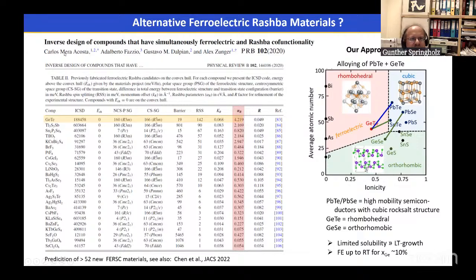Actually, there have been some recent publications by Alex Zunger's group, on inverse design of compounds with ferroelectric and Rashba functionality. And in this paper, they published a table with more than 52 compounds that they predict to be ferroelectric Rashba semiconductors. But as you see from this table here, germanium telluride is really the material with one of the highest predicted Rashba constants.